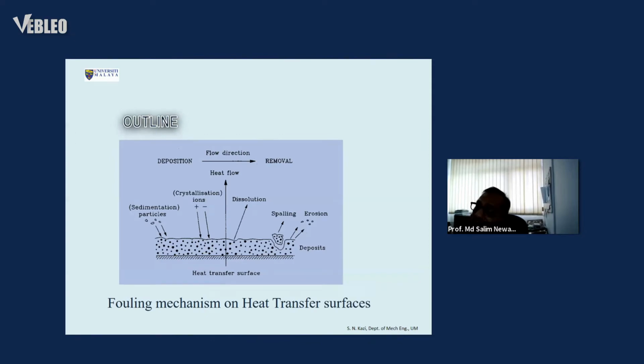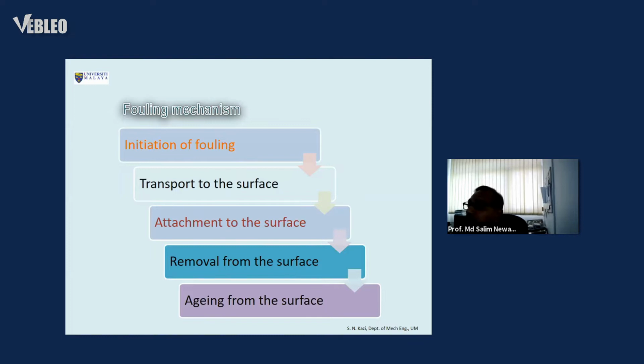Regarding the mechanism of crystallization fouling, the cations and anions of these deposit salts are attracted to the higher temperature surface, because with the temperature rise the solubility decreases. They are attracted due to electromagnetic force on the surface, and then form crystals on the surface. In course of time, crystal deposits build up, and then due to shear stress on the surface, exfoliation occurs, some percent is removed and again deposits. So this breaking and making goes on continuously unless it forms an asymptote or a steady state.